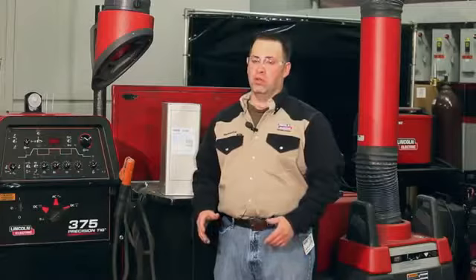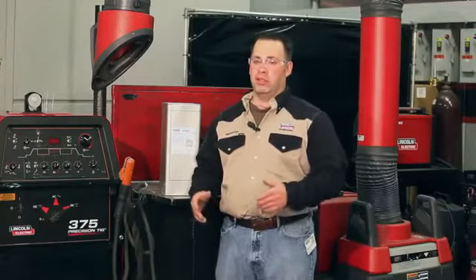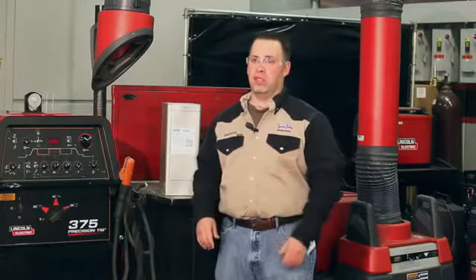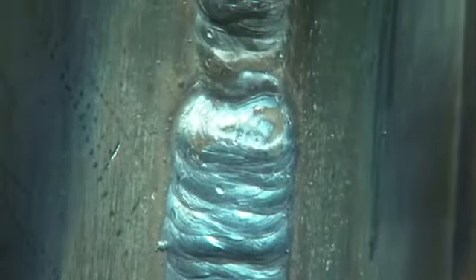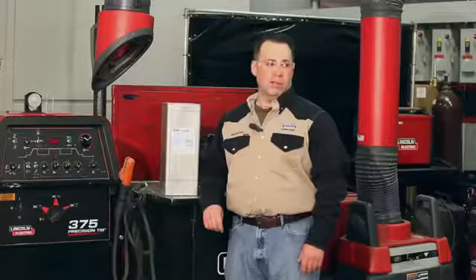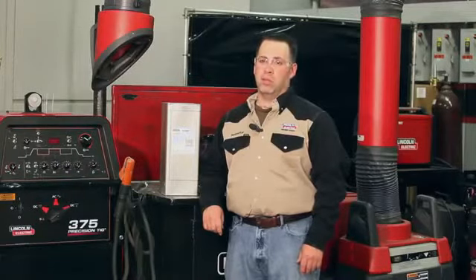If you go too slow, you're just wasting material. And if you're going too fast, you're not getting the penetration you want to get. And if you go at the right speed, you should have a nice flat face with a good wash-in. I'm going to demonstrate a 3-pass vertical up weld for you today.